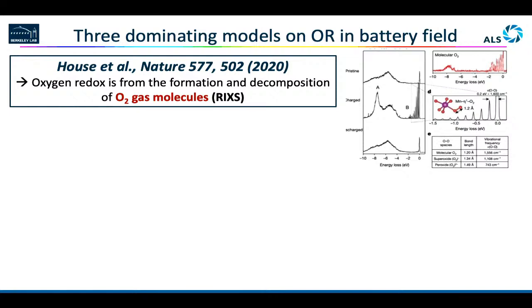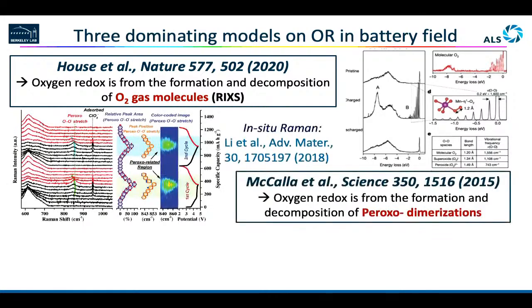To resolve those vibronic mode features and compare with the vibronic mode of molecular systems, it is very close to the oxygen gas molecule. So they concluded the oxygen redox is actually from the formation and decomposition of the oxygen gas molecule. That is one, and because it's more recent, there are more people following this model now.